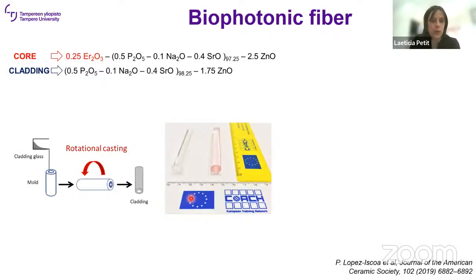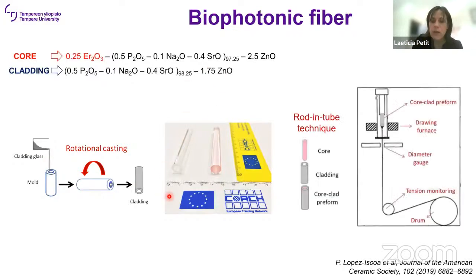So the cladding was prepared using rotational casting. So you cast the cladding in the mold and then you spin really fast, and then you have this hollow tube as shown here. Then we used the rod-in-tube technique to draw the fiber, and the fiber was obtained using a 980 degree C.